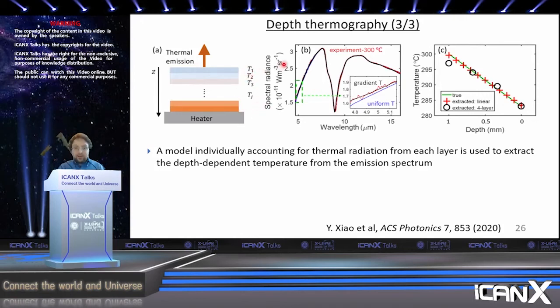So here's the experiment. This is the measured spectral radiance after all of the calibration versus wavelength. The real data, from this experiment when the temperature stage is at 300 degrees Celsius, is the red curve over here. Now, overlaid with this red curve are two other curves. It might be hard for you to see because they really fall on top of each other. If you zoom into this region over here, you see that there's this red experimental curve, but there's also this black curve and this blue curve, and these are theoretical fits to the data.